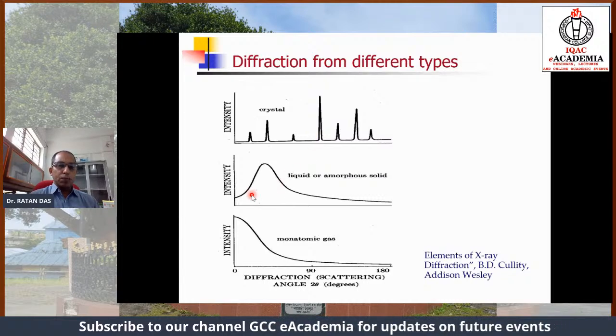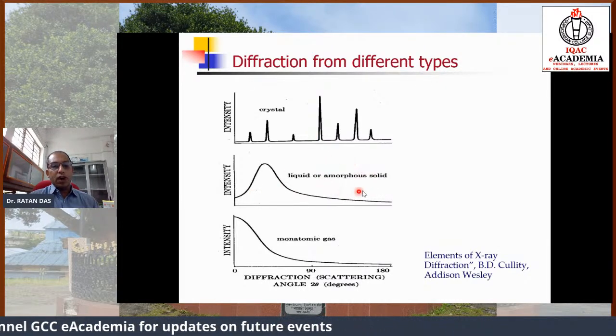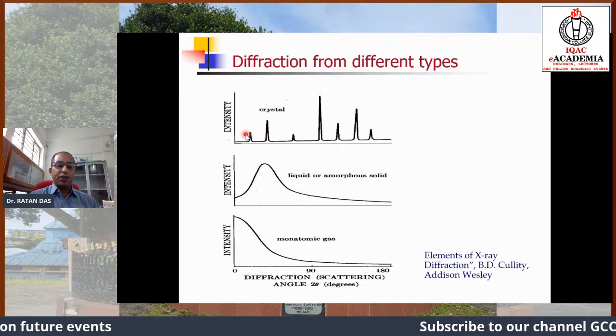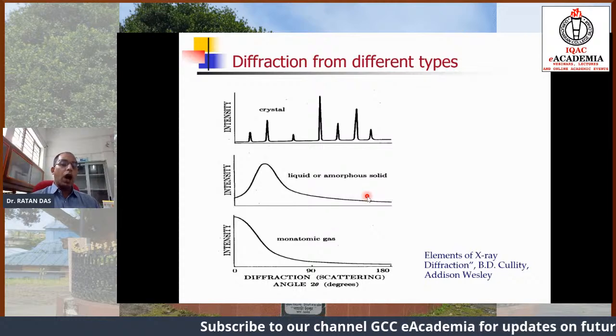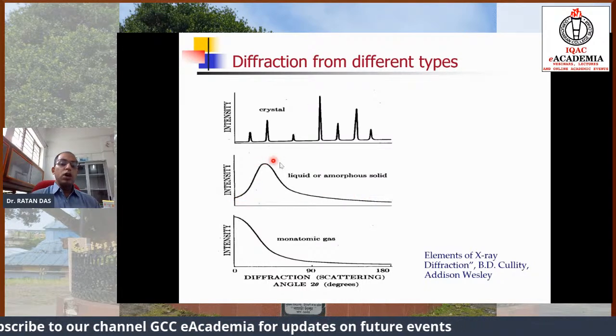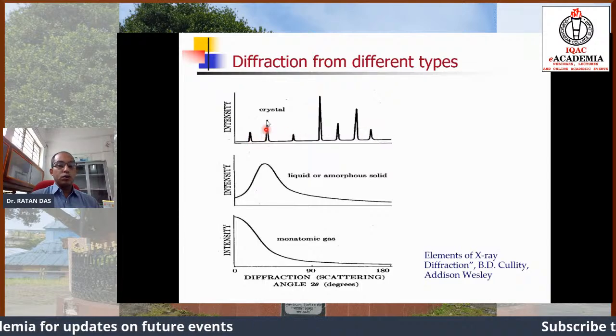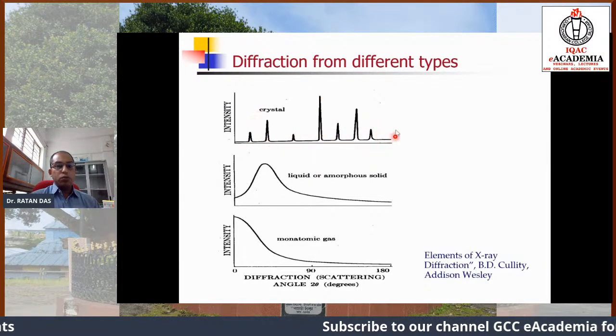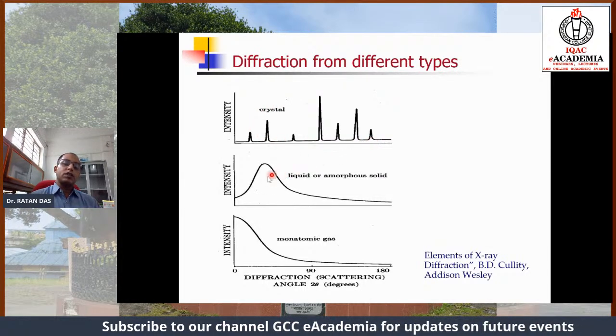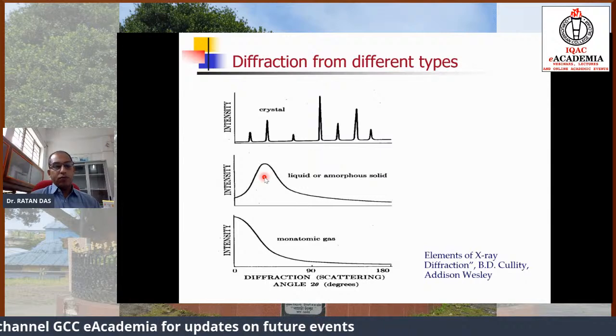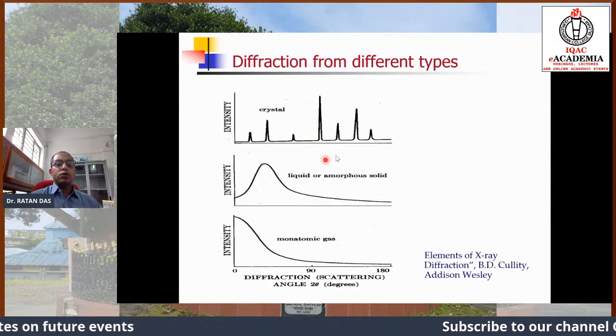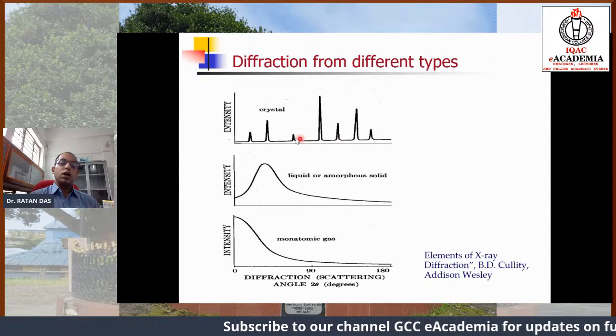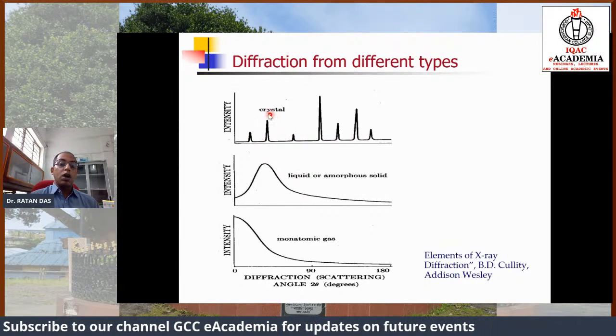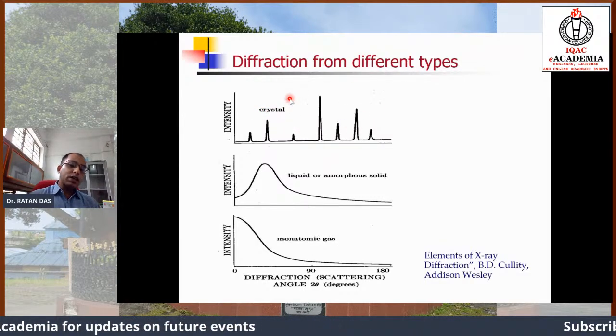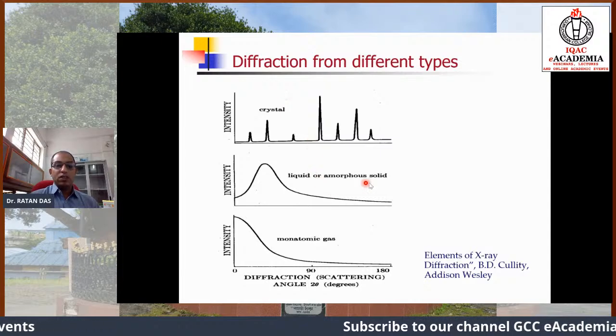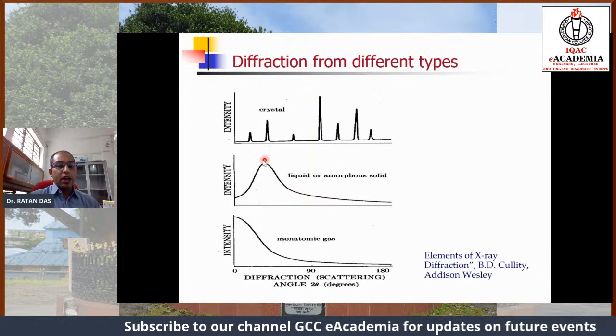But if it is a liquid sample or amorphous, this is very important. If it is amorphous, then we never get such peaks in the diffraction pattern, and we get a huge, big hump in the diffraction pattern. No way can we get these small peaks in the diffraction pattern. If such small peaks are not available in the diffraction pattern, then we can certainly say that the prepared sample is amorphous. As a nanoparticle researcher, I am interested in the structure where the sample is crystalline in nature. But there are other researchers who study the amorphous nature of the sample; they will be happy if they get a pattern like this.